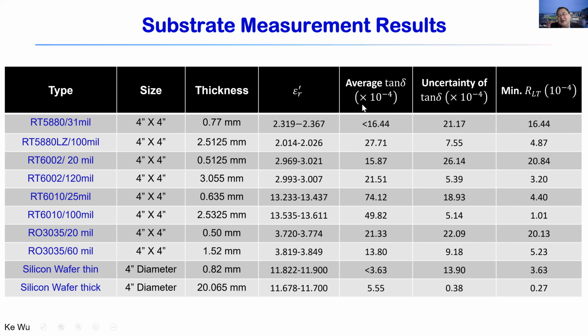So this is 10 to the minus 4 values. The uncertainty is given here. We can see the minimum loss tangent resolution value here. So based on this value, you can see how accurate you can get. For example, for thicker silicon wafers, you can guarantee very good loss tangent accuracy. We are more interested in loss tangent than the real part, because for the real part we have pretty good values obtained through these quasi-optical measurements.